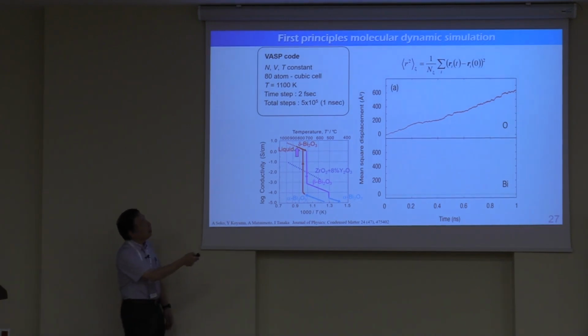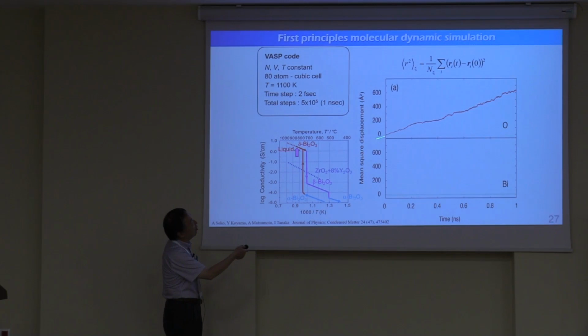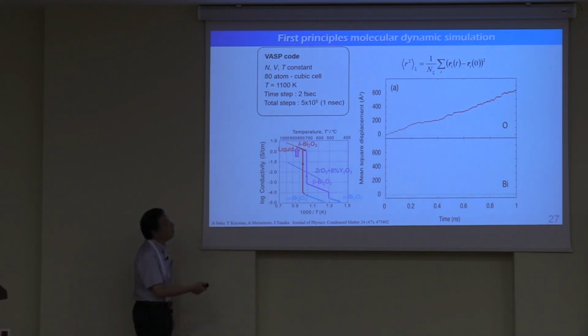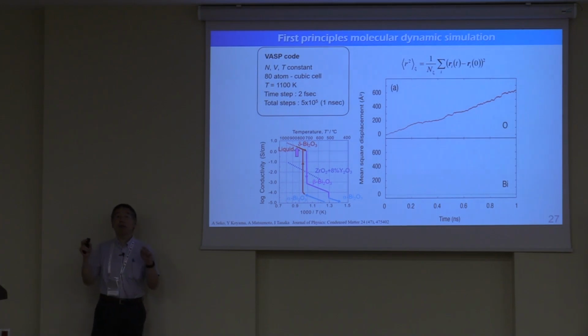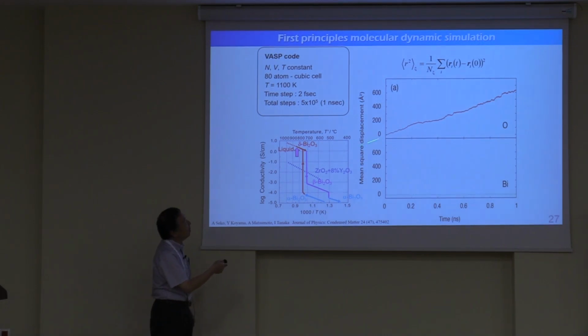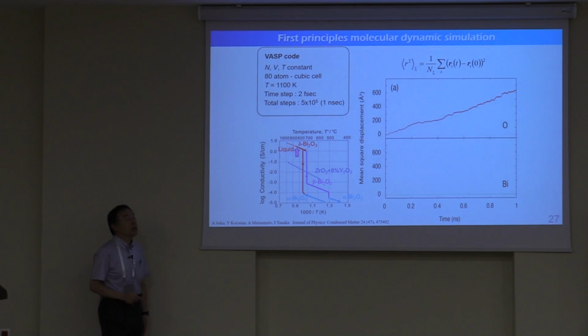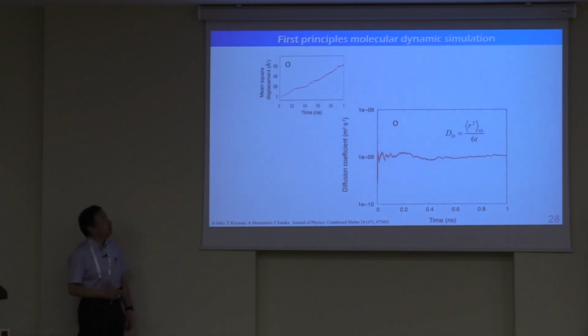You can see that only oxygen shows an almost linear increase in mean square displacement like that. Bismuth doesn't move around. Bismuth showed some kind of thermal vibration, but bismuth cannot move around. But oxygen can move around, and from this slope, we can estimate the diffusivity.